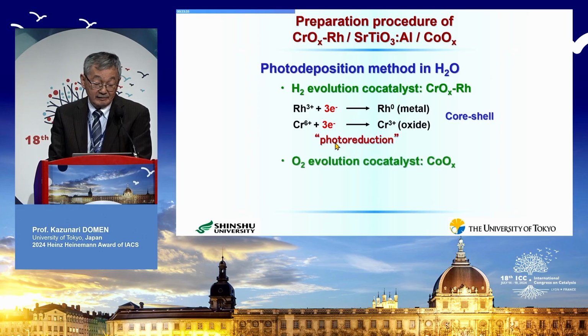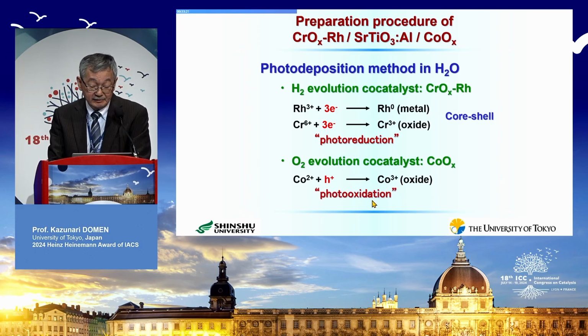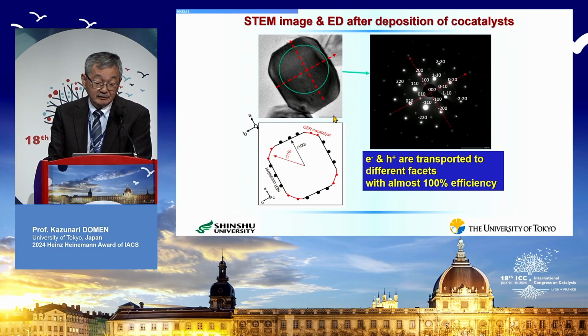After that, we construct the oxygen evolution co-catalyst. That is a cobalt oxide. In this case, we use photoexcited holes to oxidize cobalt-2+ into cobalt-3+. More precisely, cobalt oxide. So this reaction is a so-called photooxidation reaction. So during this modification, we examined what happened on our photocatalyst by using high-resolution STEM images.